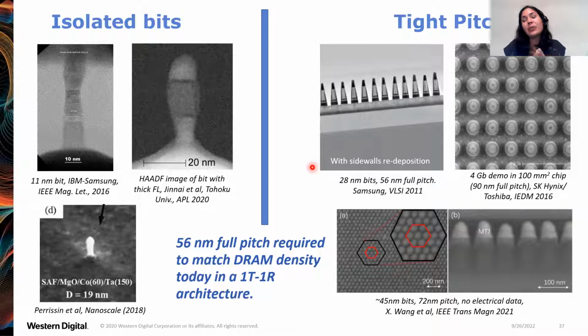To make an MRAM bit, you need to remove a lot of metal material by milling. And this metal material, when it gets removed, gets redeposited on the sidewalls of the pillar and shorts out the barrier, so that you get nothing but shorted bits and no electrical data. That's what happened here for this Samsung demo. They have the tight pitch array, but with all the sidewall redeposition, there's no electrical data.